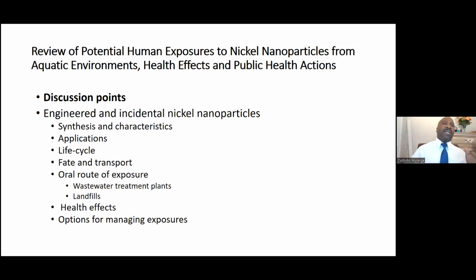The good news is that most of the waste treatment plant technologies that we have in the United States and many developed countries are very efficient. We have a removal of metal-based nanoparticles in general of about 90%. It is true that for nickel nanoparticles it is a little lower, around 78%. Then they are removed and go to the surface water streams. We also have drinking water systems that are very efficient, and with advanced technologies they can remove some as well.